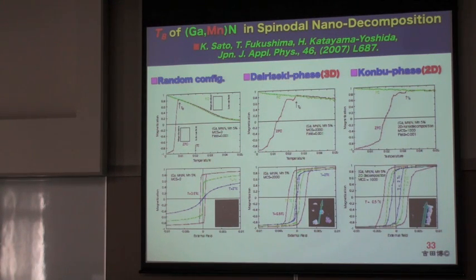In this case, shape and also magnetocrystalline anisotropy, this becomes very long, and then this becomes very large. In order to flip the magnetization, you can see the blocking temperature increases very dramatically compared with the disordered system like this. In this case, the system is completely superparamagnetic, not ferromagnetic, because this nanowire and another nanowire cannot talk to each other ferromagnetically.